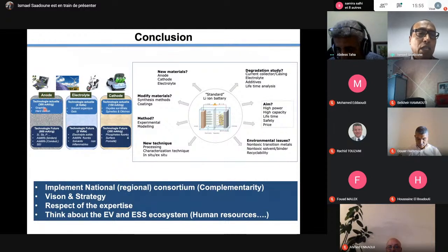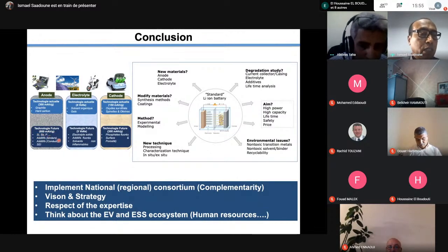On the anode side, we have 300 mAh per gram, we use graphite, sometimes hard carbon, but in the future we should have 600 mAh per gram using phosphorus, silicon, antimony, and some additives for conductivity.